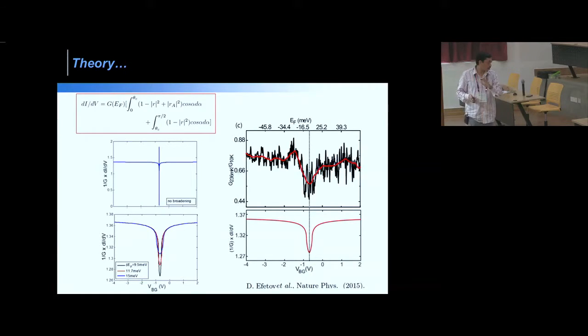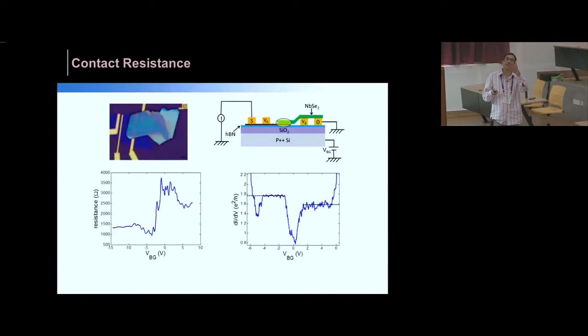So this is the first part of my talk, where I talked mostly about how the Andreev reflection happens near the Dirac point, in particular the transition from retro to non-retro type of Andreev reflection, and the suppression is a signature of that. I'll not go into details about the effect of contact resistance, but I'll just mention usually the contact resistance between graphene and gold is less than 100 ohm, and gold with NbSe2 is also less than 100 ohm. Only graphene with NbSe2, we have a contact resistance of the order of 2 kilo ohm.